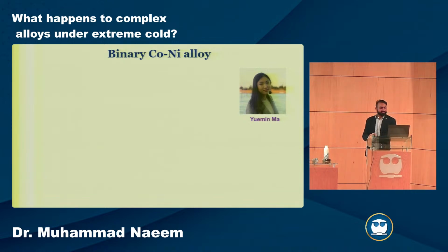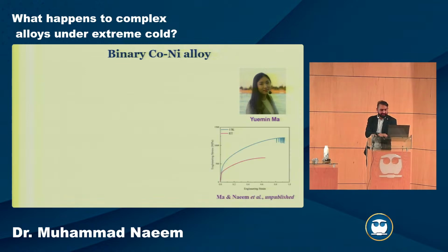Then another project of hers was looking at cobalt nickel, because we were going up to the chromium cobalt nickel ternary, and now we wanted to simplify it to understand mechanisms, because it's much easier to do in simple elements, maybe not that easy still, than in really complicated systems. So we picked one system, cobalt nickel, which was FCC. Cobalt 35, nickel 65 in atomic percent. This is a very simple system, because the increase in ductility was somehow associated with these multi-component high entropy alloys. But this is a very simple system, and still you see an increase in strength as well as ductility at low temperature. And this was very interesting to us.